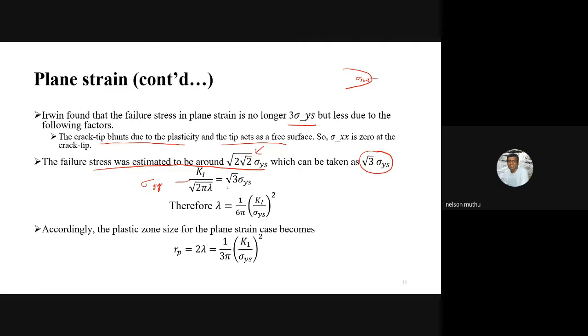And then when you use the expressions on the right hand side, because of the above mentioned reasons, you are going to get the value of lambda as 1 by 6 pi (K1 by sigma_ys) whole square. But still, the size of the plastic zone is lesser in the case of plane strain compared to plane stress. Right? So now, if you want to use the second order estimate, like in the case of plane stress, to achieve equilibrium, you will get an expression like this: Rp is equal to 2 lambda. So in the case of plane strain, your Rp is going to be 1 by 3 pi (K1 by sigma_ys) whole square. So that is the contrast between plane stress and plane strain.